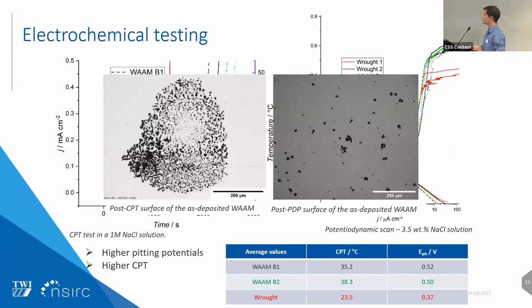As for the pit shapes, this is a pit observed after CPT testing, and on the other image you can see pits formed during the potentiodynamic polarization. We can see that we have a selective dissolution of the austenite here, with bits of ferrite remaining, and that has been observed using an SEM microscope.